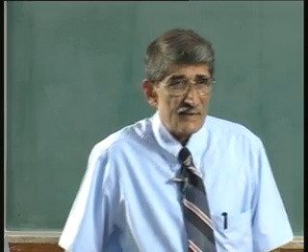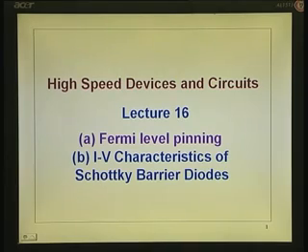In the sense, they are located above the donor level. This we have illustrated with an example of gold in silicon, because gold can be a donor or acceptor, and there those deep donors are 0.3 electron volts above the valence band, and deep acceptors are mid gap. So, with that we understood, and we also began some discussion on the